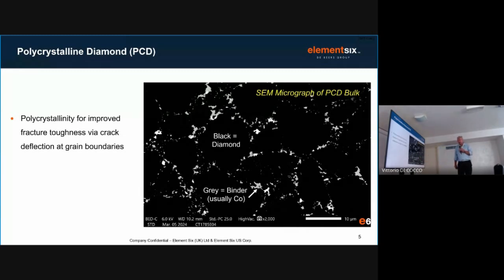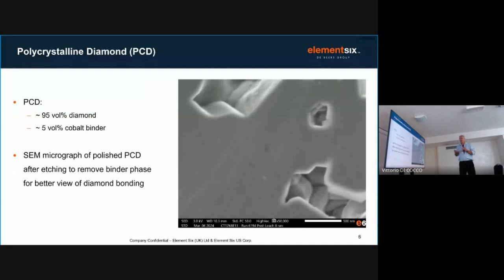So what we get with polycrystalline is crack deflection. So that pushes our fracture toughness up. It's still not earth-shattering, but it's good enough fracture toughness for us to now have a tool. So if you have in your mind, then you think about polycrystalline diamond, just think 95% diamond and about 5 volume percent of binder. So here I've got a picture.